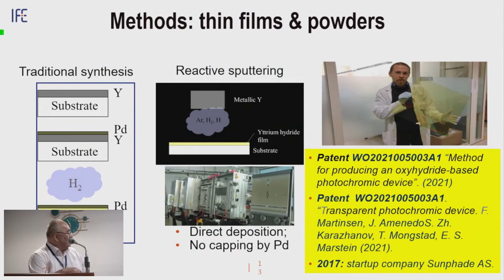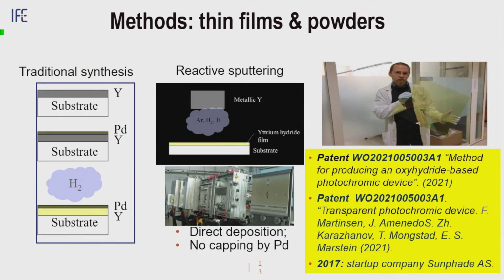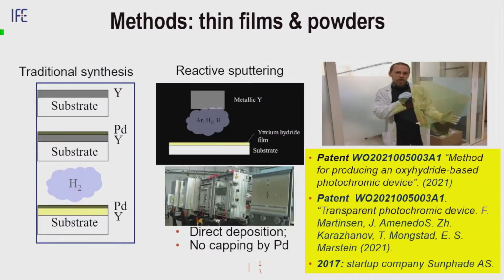Yes, before us, study of this material was already ongoing. However, a different deposition route has been used. First, on a substrate, an yttrium thin film was deposited, and then it was encapsulated by palladium. And then yttrium was hydrogenated through the palladium layer.